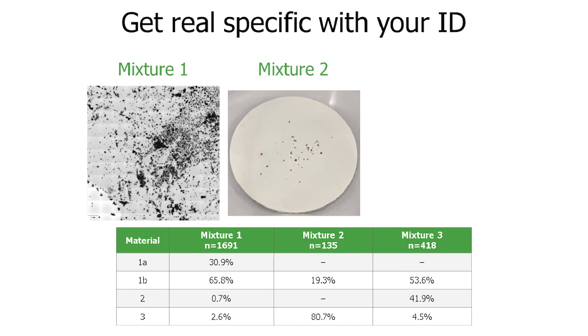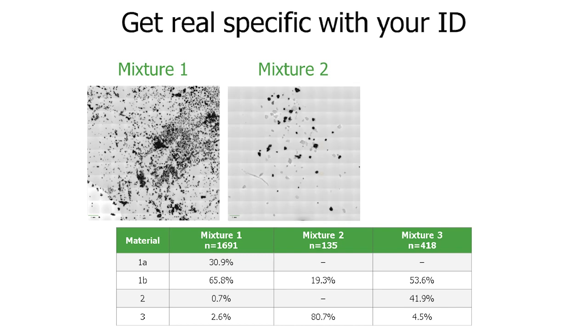Mixture 2 had fewer particles, but these particles were a lot larger. For mixture 2, 135 particles were identified, and a large majority of these were material 3. Just about a fifth of the particles were found to be material 1B, and materials 1A and 2 were not present at all in this mixture.